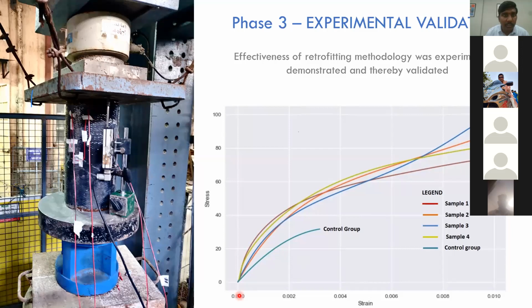So this is a stress-strain curve that you're seeing. Strain on the horizontal axis and stress on the vertical axis. So up to a strain of 0.01, the FRP wrapped concrete was performing, and it was going further. The curve was extending still further, and you can see that it was reaching 70 MPa strength, 100 MPa strength, etc. But here you can see that the control group, which is not FRP wrapped, is reaching only up to this much strain, after which it was breaking. This curve is the average of 3 different unwrapped samples, as in plain concrete samples. You can see cylinder strength is around 32, which means it might be around M35 or M40 concrete. So it was only going up to here.